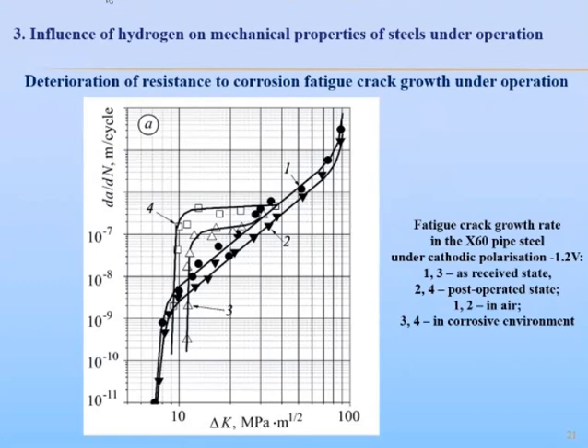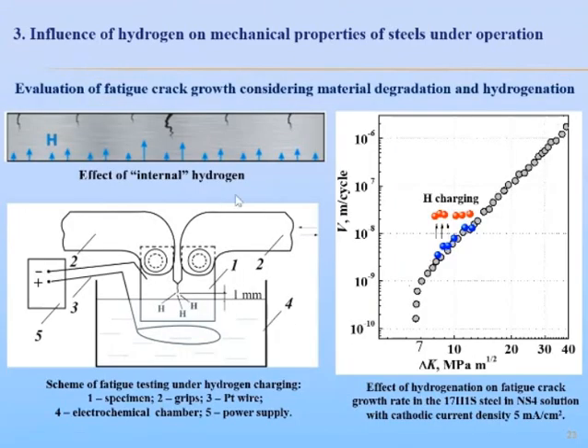It means that fatigue growth is significantly induced by sustained load. And here is demonstrated the effect of internal hydrogen on fatigue growth in the operated pipeline steel, when hydrogen diffuses to a prefracture zone through the bulk metal.